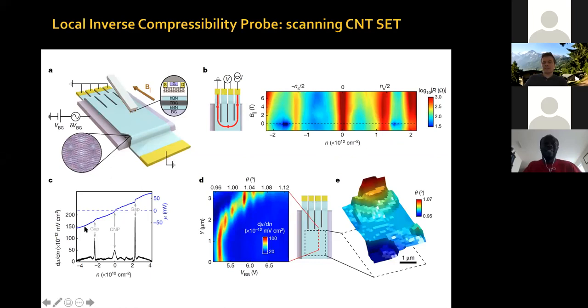So you can see that the chemical potential for magic angle graphene has these steps at the band insulator. Let's focus on this step here. You reach the top of your conduction band, the flat band, then there's a band gap, and then the remote band starts. So the chemical potential jumps very fast at this point, as you go from the top of the conduction band to the bottom of the valence band of the next band. And the chemical potential exhibits a given behavior also across the charge neutrality point.